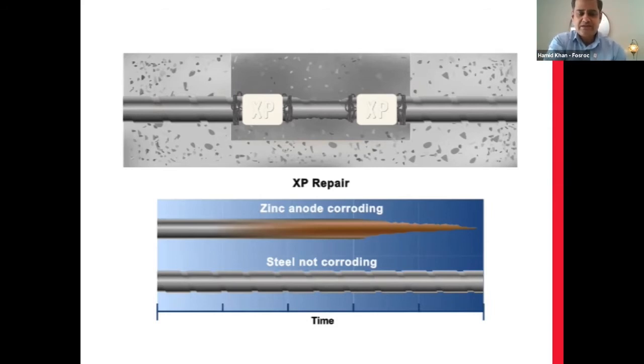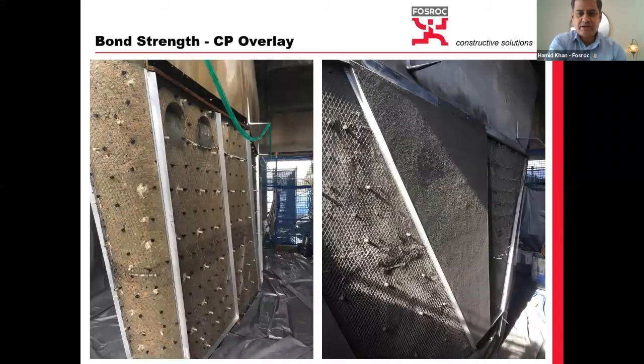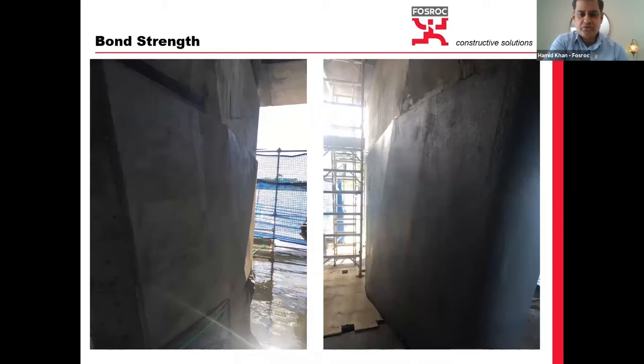As we are talking about side effects, I just thought I'd mention it. Now coming back to the bond strength, which is required for the integrity of the repair mortar. These are some of the projects that I was involved in, where the CP overlay was sprayed on. Again, it's very important to have very good surface preparation as outlined in the standard, because these are spray applied. These are not traditional saw cut and repaired mortars. When we are talking of an overlay, the concrete substrate must be prepared to at least CSP 8 or 9 or similar.